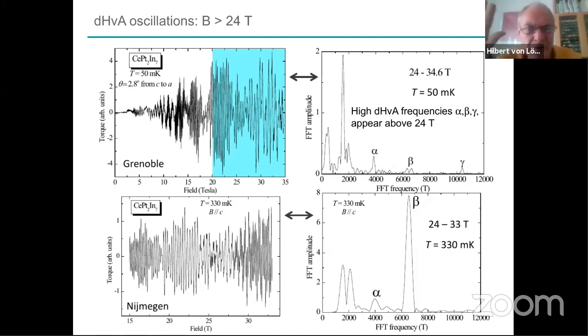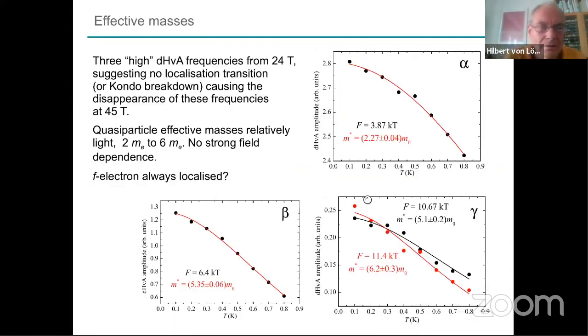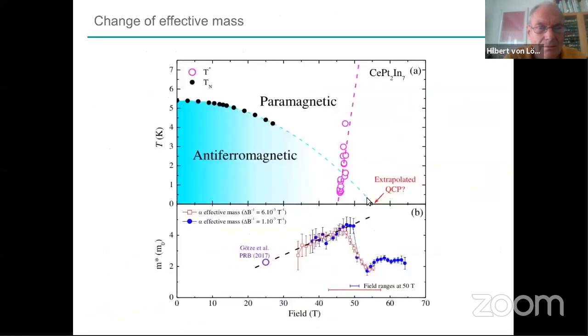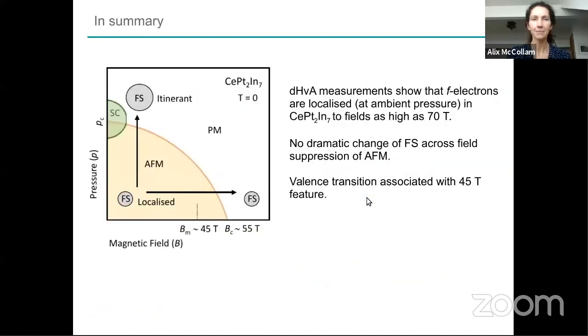I have a question concerning your last slide. Could you go back to that, please? This one? Yeah, right. If you go horizontally with increasing field, you don't see much change of the Fermi surface, Fermi volume rather. But if you go at constant field with increasing pressure, you seem to indicate that you go from a small Fermi volume to a large Fermi volume, much like then there could be some sort of T-star line or something like that. What's the evidence for this crossover from a small to a large Fermi volume?